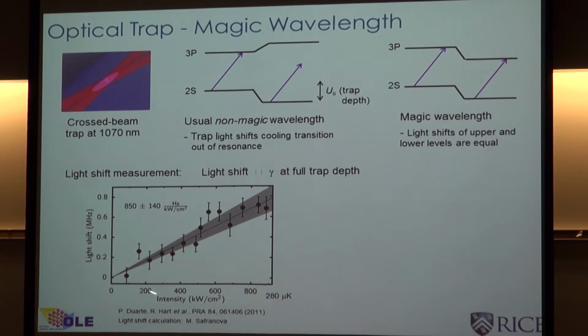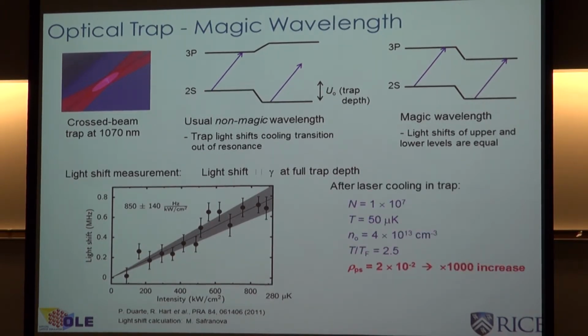This is a kilowatt per square centimeter of light intensity. And the light shift is only less than a line width, less than a megahertz. And so this is a really huge advantage. Now, instead of increasing our phase space density by a factor of 10, we're actually able to increase it by about a factor of 1,000. So we can do laser cooling in the trap and get very high phase space densities, which are excellent starting points for doing evaporative cooling.